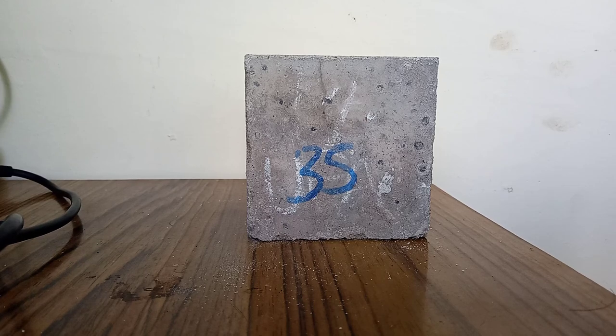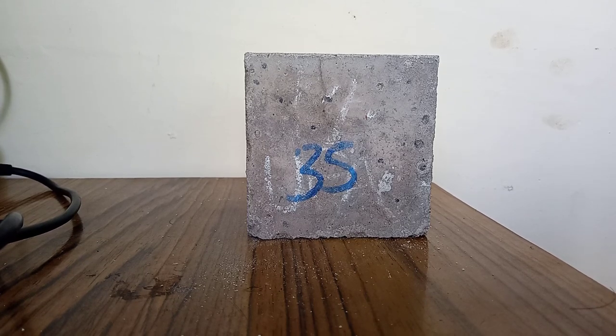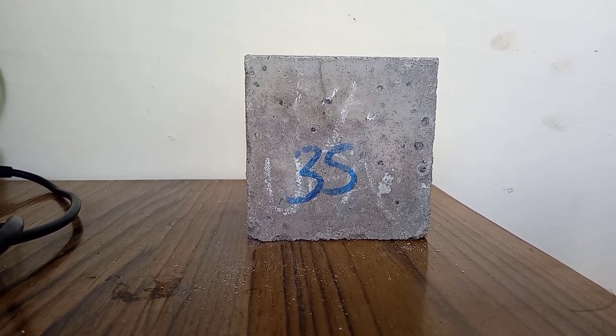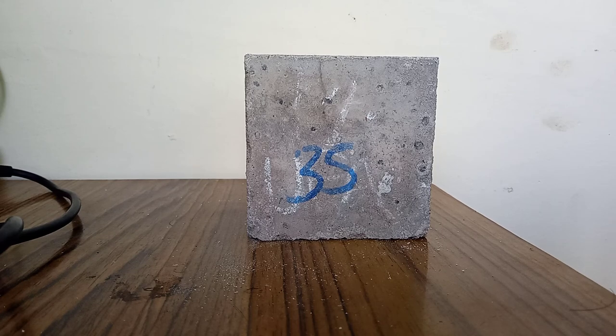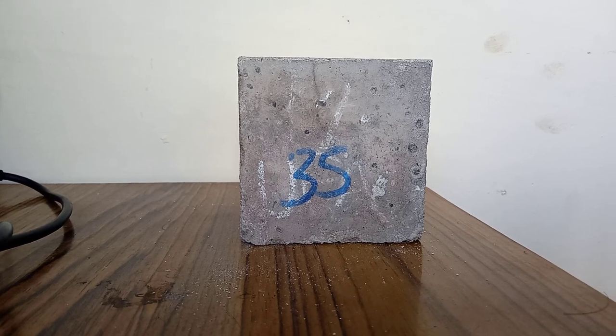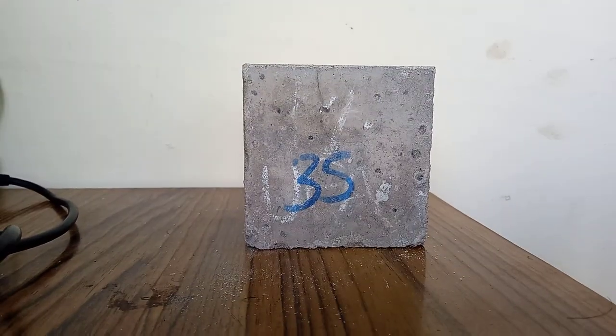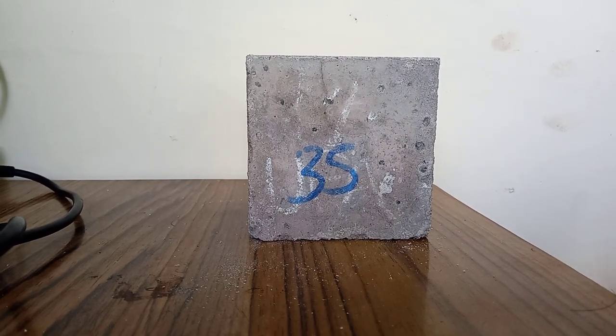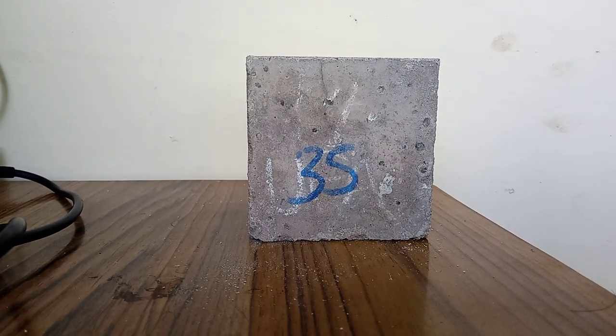To assess the durability properties of the developed biomass replaced geopolymer concrete, water absorption, sorptivity, and rapid chloride penetration tests were carried out. Also, the thermal conductivity and fire exposure tests were conducted to examine the thermal behavior. From the results, it was inferred that the 10% sugarcane bagasse ash replaced geopolymer concrete specimen exhibited the maximum compressive strength of 36.8 MPa, which is almost similar to that of conventional fly ash based geopolymer concrete.